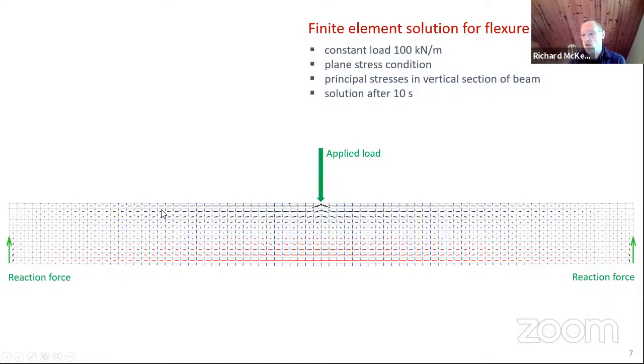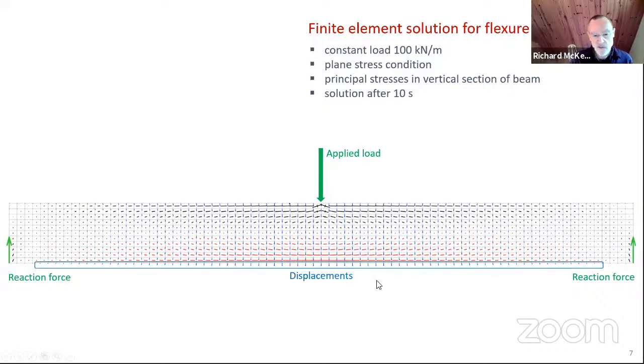The reason why I've shown 10 seconds is because that's approximately the time scale for if you're bending an ice sheet up against a sloping structure, or for flexure under wave action in the ocean. And in this figure, if you look carefully at the bottom, I've actually shown displacements at all the nodes in the model, and those are little blue arrows. The maximum displacement is at the center of the beam under the applied load.